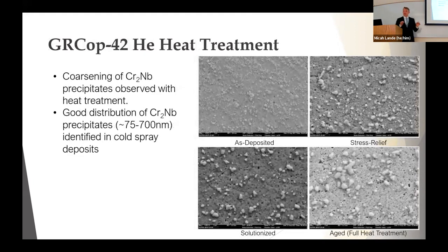Then we see something similar but different happening with GRCOP42 as it goes through the heat treatment process. At the very start, we can see, like I said before, all of these secondary phases, these little tiny dots. They're very, very small, ranging between about 100 and 700 nanometers, so less than a micron in diameter. However, as we go through our heat treatment process, we see these particles begin to grow, and they begin to gravitate together to make bigger, coarser particles.